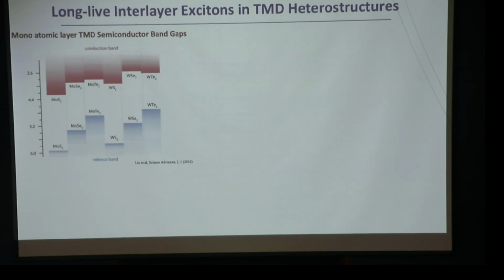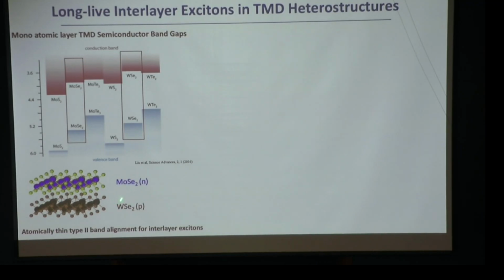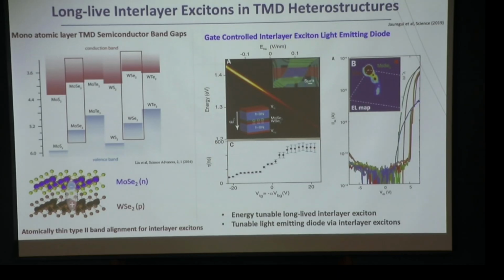Because by just choosing the right semiconductors, something like tungsten diselenide and molybdenum diselenide in this way, they can immediately form so-called type 2 alignment, which means once you excite the system by light or inject electrons and holes into the system, they readily form the interlayer exciton, which was studied quite well by that one group here, right? And moreover, this interlayer exciton can be quite long-lived. And also, when we form these device structures, which I showed you a few slides back, you can control the interlayer exciton energies by applying the electric field. In the same way, the gate voltage can control this lifetime. Moreover, the lifetime is fairly long, about even half a microsecond, or even longer lifetimes can be achieved.